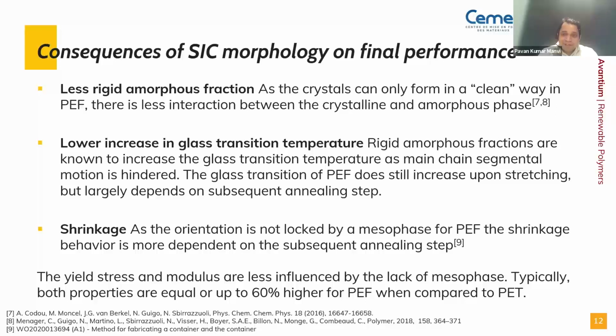So this is a big difference, because the amorphous region is very clean and there is no mesophase which can control the amorphous region. So shrinkage behavior is very prominent, and it also depends on the whole structure, on how the final interaction between the amorphous and the crystalline phase is. But due to the clean amorphous region and clean crystalline region, it is necessary to arrange the morphology in a way that the shrinkage can be brought to the required level. So all this morphological history is influencing the mechanical property and also the shrinkage property, that we will see in the coming slides.